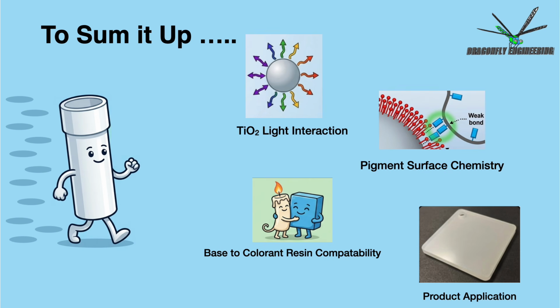Okay, folks, it's time to sum it up. We discussed why the band gap and refractive index of titanium dioxide make it the best material for white pigment. We covered how white pigment particles are made and why surface functionalization tailored to the use case is important for pigment dispersion in the plastic matrix. We covered thermal and chemical aspects of compatibility between the colorant resin and the base resin, as well as how these pairing choices can impact part quality.